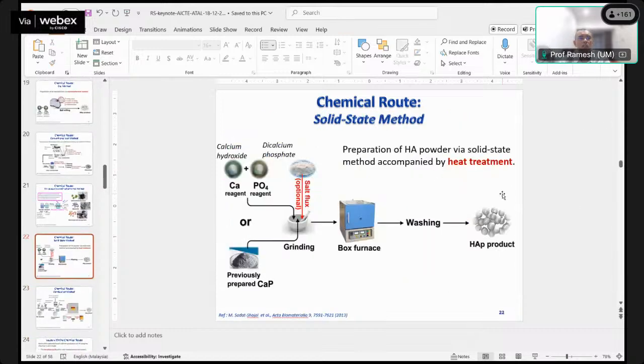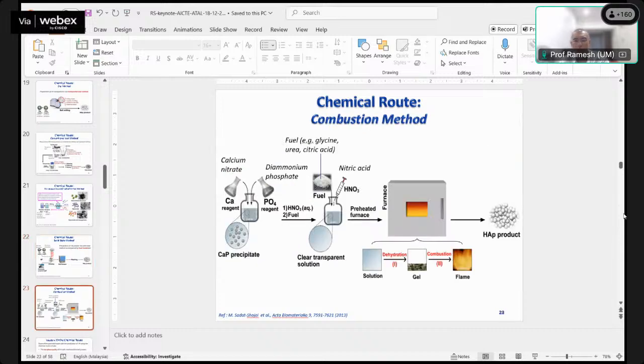All right, then you have the solid state method. Solid state method, very straightforward. Mix two items together, put it in a furnace and wash it. You get the hydroxyapatite powder. So that's the solid state method. Then you have the combustion method. This I have done, using a fuel. We use glycine. So you mix calcium nitrate with diammonium phosphate. You can try it in your lab.